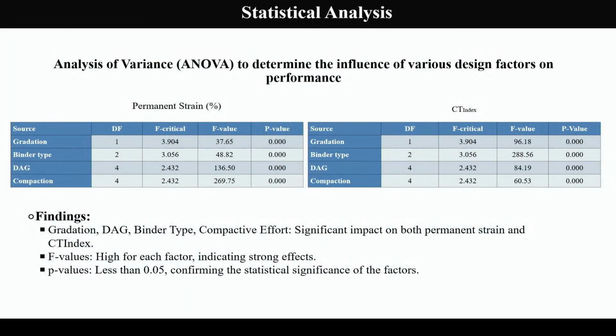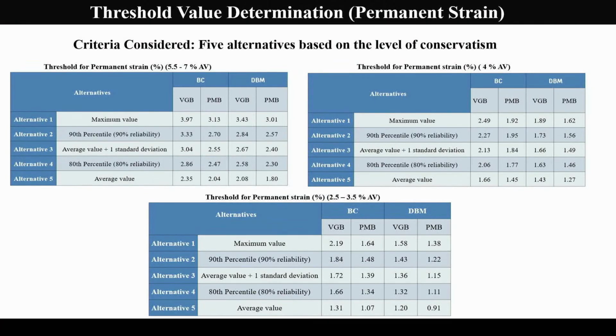We did some statistical analysis using ANOVA, and as Sridhar Raju sir pointed out, the compaction can play a very important role in the design. So in the rutting, we found that compaction has a higher F value, which denotes its significance. All the factors were significant, but the higher F value indicates the stronger one. If we choose the minimum one, that could be the most conservative one, because all will pass. And if you choose the alternative, the average, half of the mixtures will be discarded.